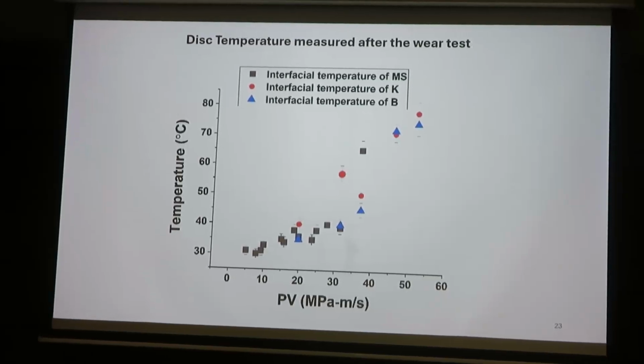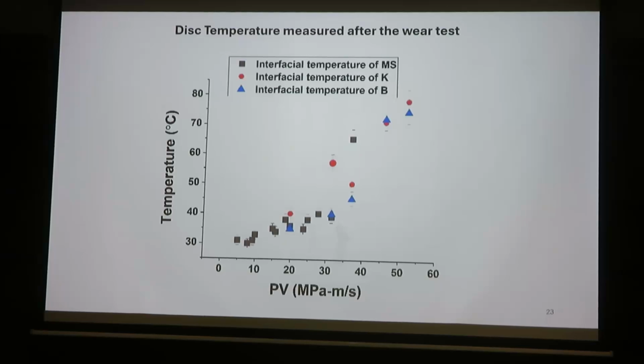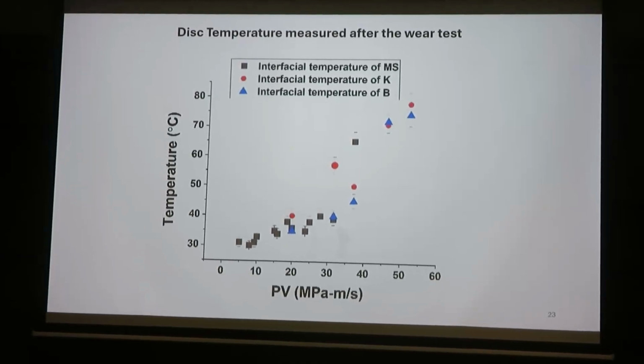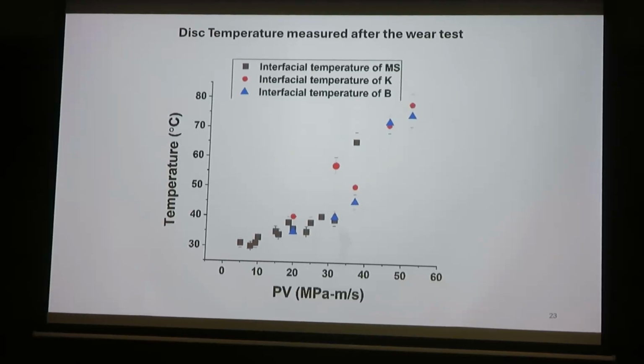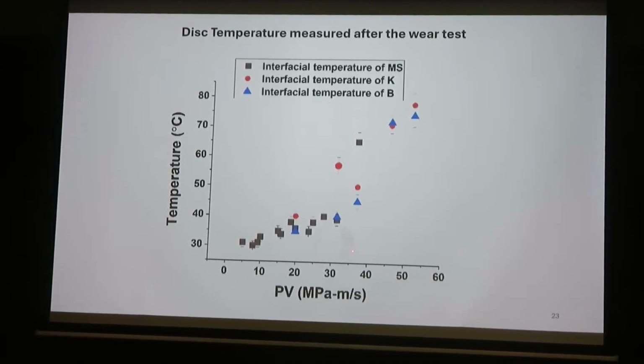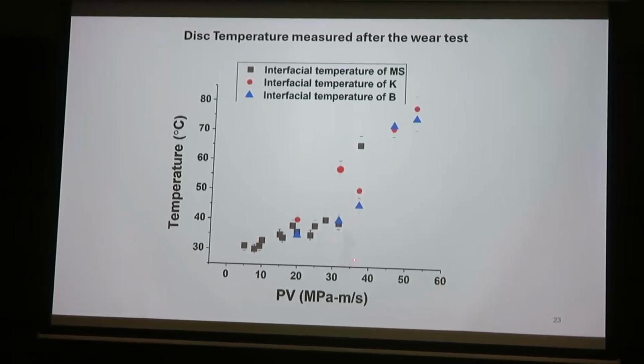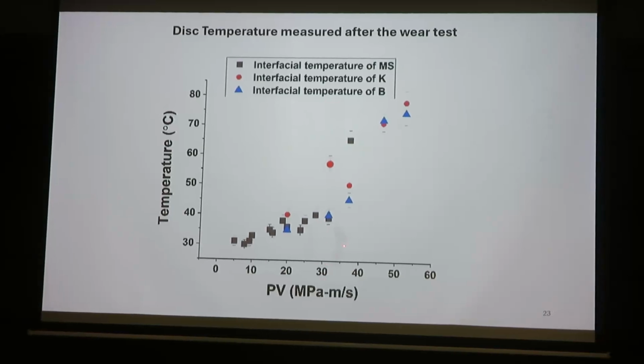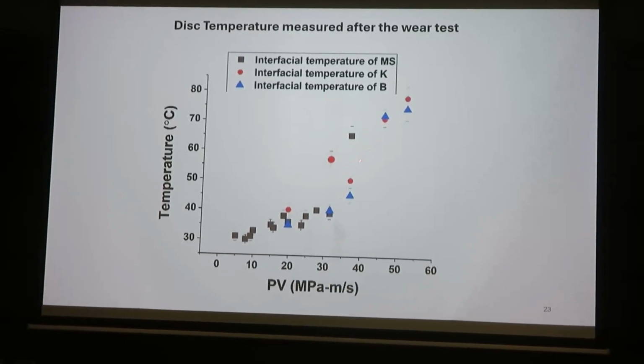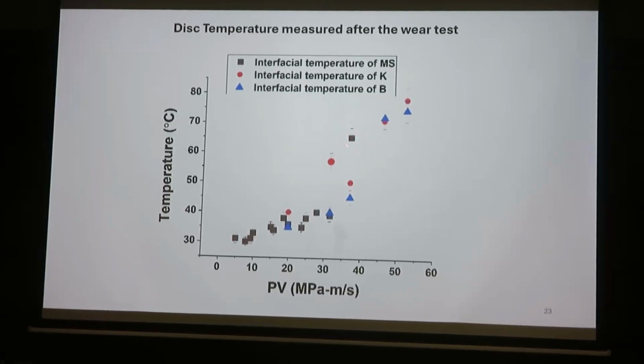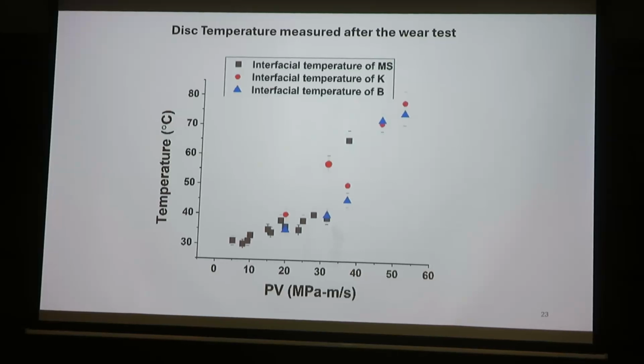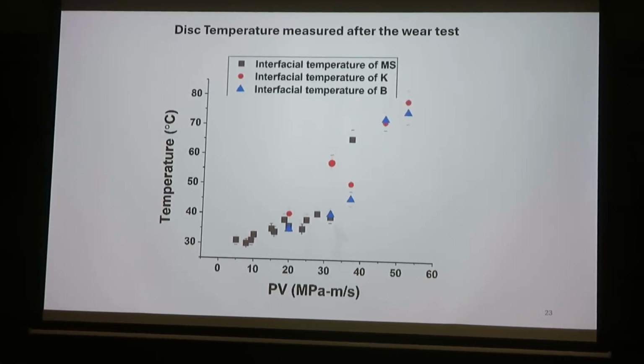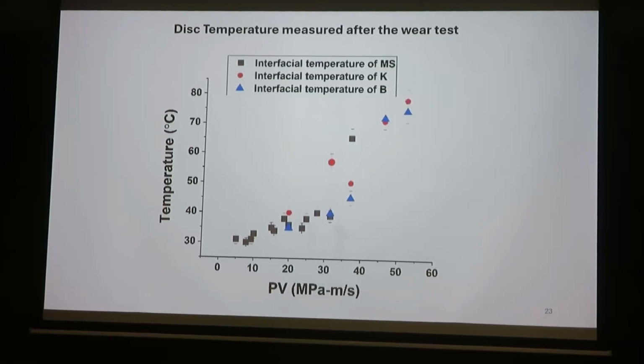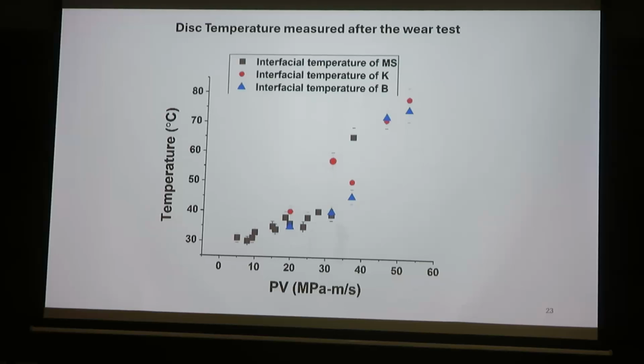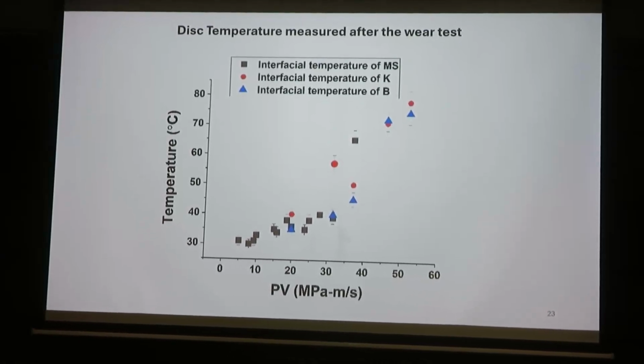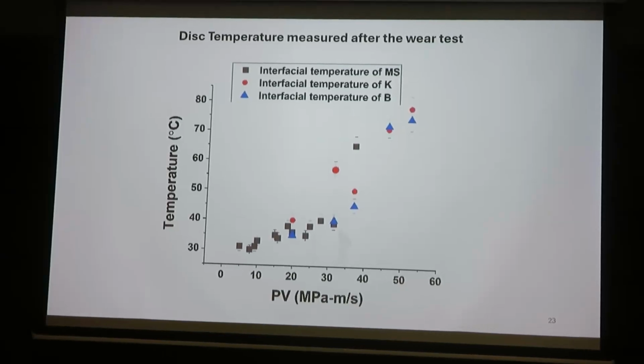And we measured the temperature, but it was actually the disk temperature after the test. So you stop the test and immediately you take the surface temperature. And you can see that there is a drastic increase in the interfacial temperature around here, at 37 PV, which indicates why one of the composites, MS, actually failed at this point, because the temperature simply starts going too high, and the failure is because of the thermal effect. So this says that if we can increase the thermal conductivity of the material, then it is good in terms of tribology. It can survive much higher PV factor.